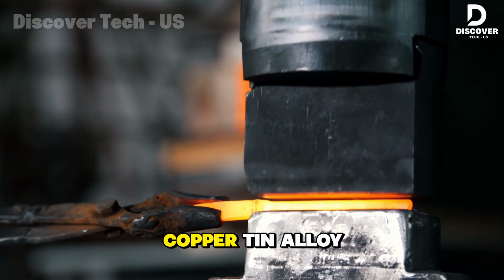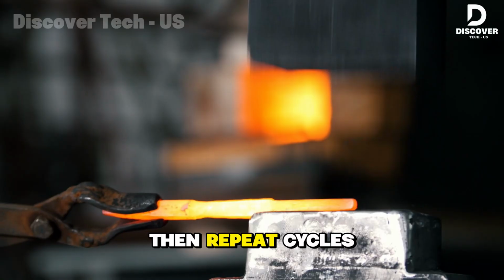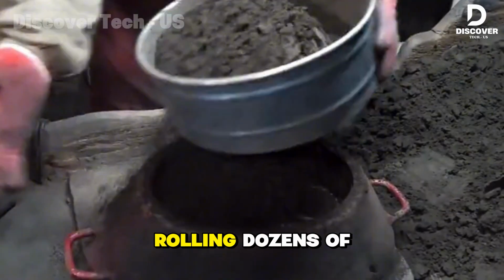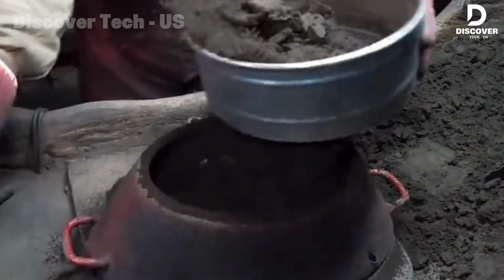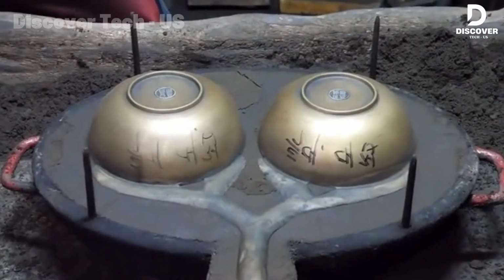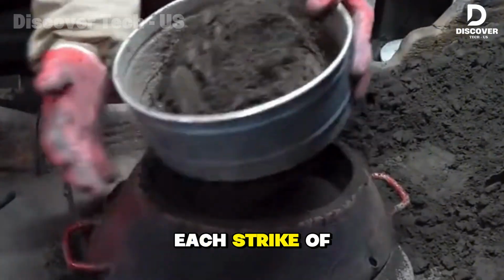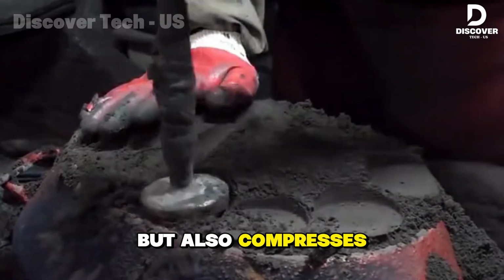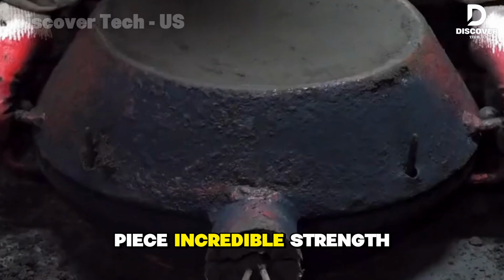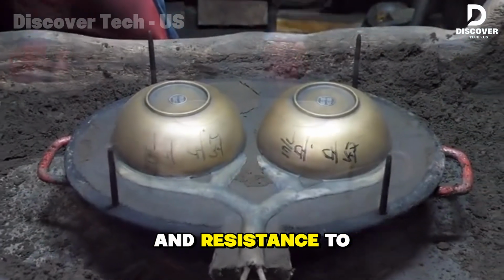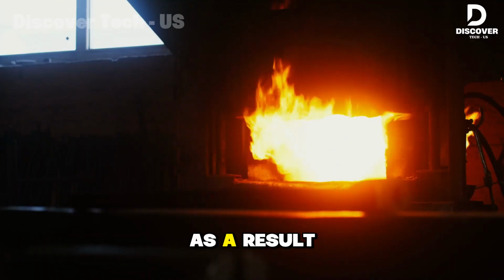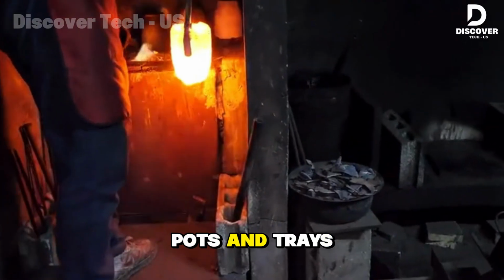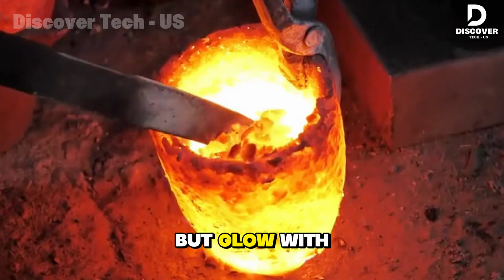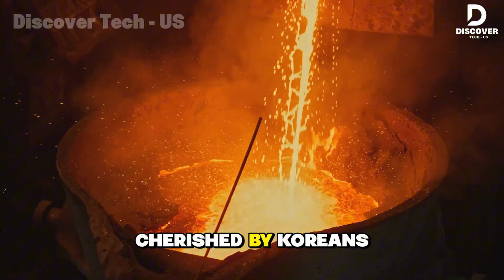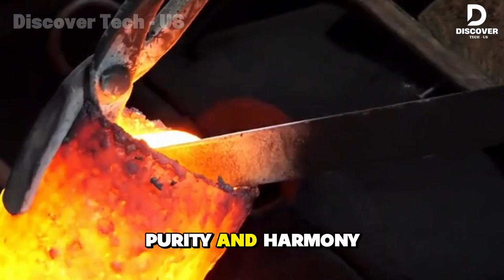Unlike ordinary casting, which is done once and finished, artisans melt a copper tin alloy and pour it into rough molds, then repeat cycles of heating, hammering, and hand rolling dozens of times. Each strike of the hammer not only shapes the vessel, but also compresses the metal's grain, giving the final piece incredible strength, even heat distribution, and resistance to warping over time. As a result, Bangja bowls, spoons, pots, and trays are not only durable but glow with a soft, golden warmth, cherished by Koreans as symbols of prosperity, purity, and harmony.